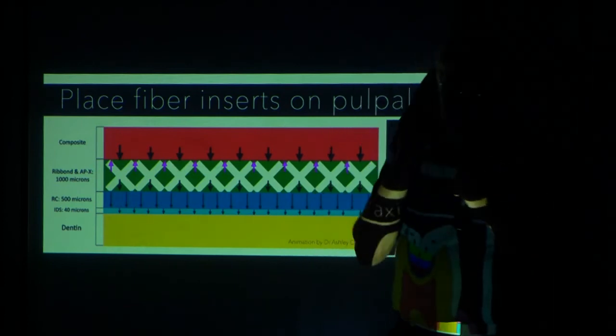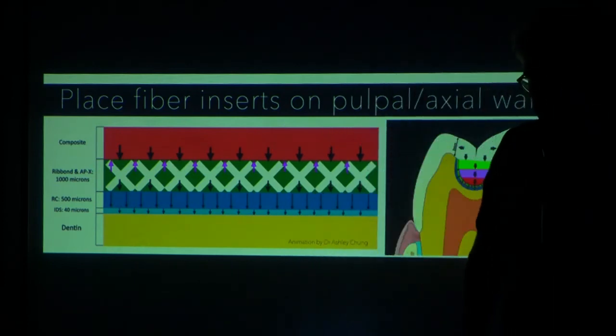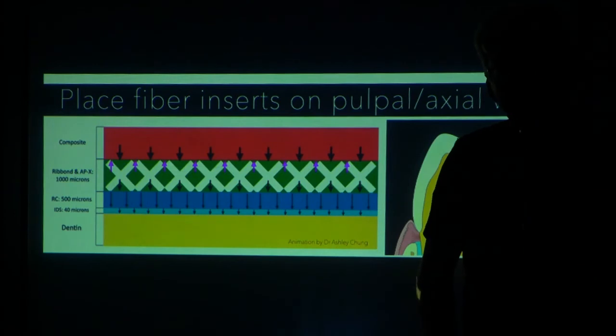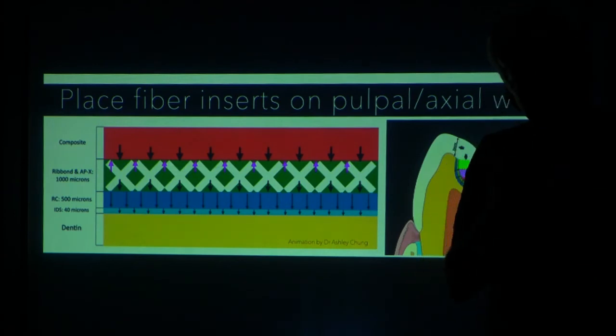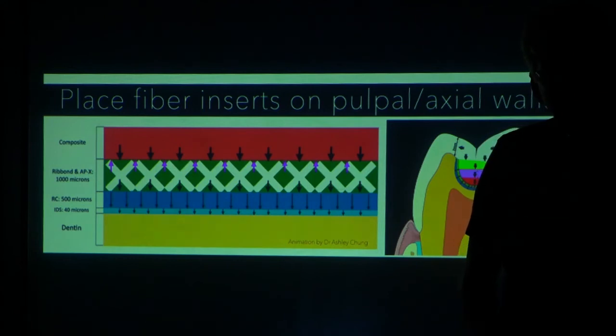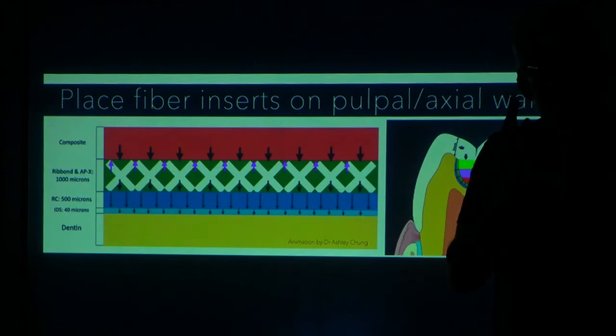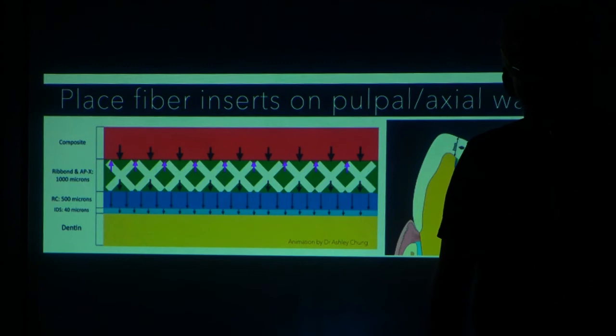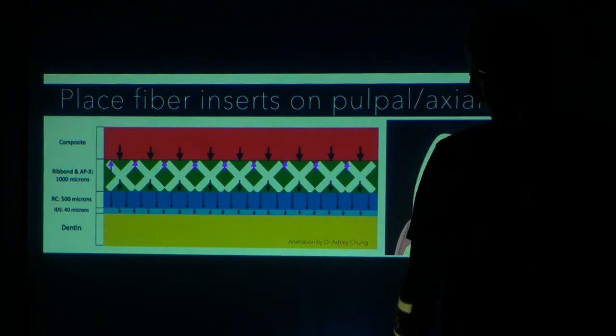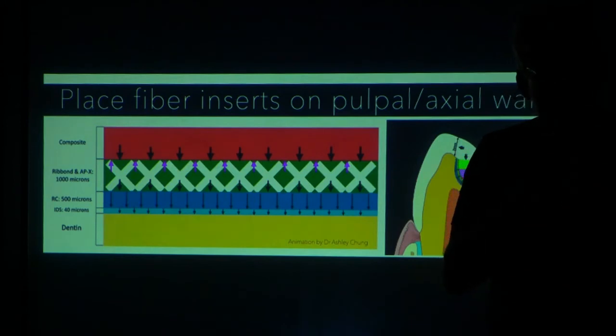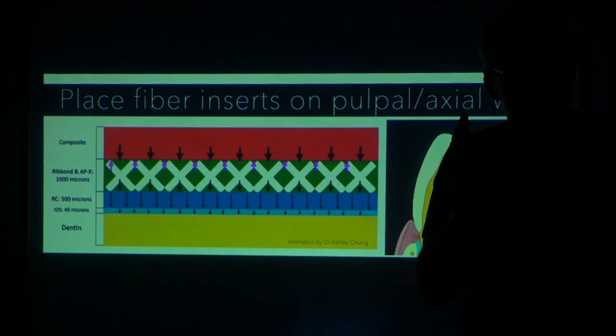And this was demonstrated by an endodontic team out of Turkey named Erkut. Erkut showed this in ribbon posts on endodontically treated teeth, which have huge C factors. You see an endodontically treated anterior incisor. What's the ratio of the bonded to unbonded surface in that condition? It's very, very high. And so the stresses of composite are going to go one of three places, right? The hybrid layer, the massive composite, or the tooth is going to be strained inward.